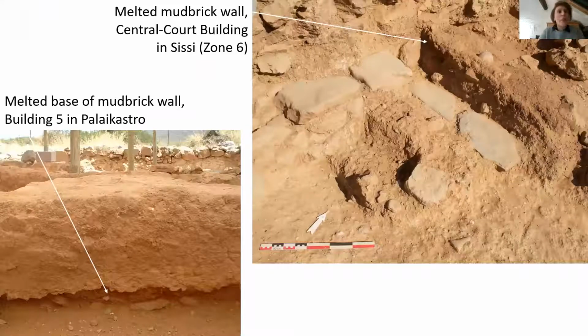Voila. Minoan mudbricks are sun-dried instead of being fired in a kiln. This makes it possible to speed up the production process, but it has a major hindrance, namely that unless they are located near a constant source of heat or baked in a heavy destruction by fire, the mudbricks melt. For this reason, this building material is often missing from standing architectural remains and hence from excavation reports and synthetic publications on Minoan architecture.